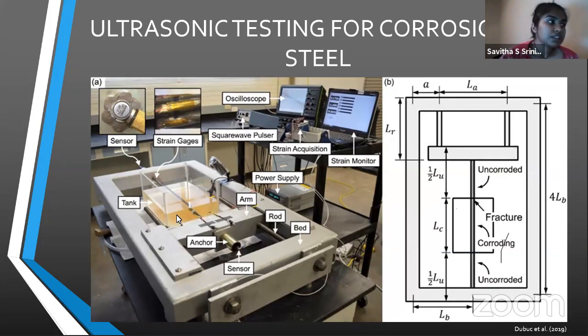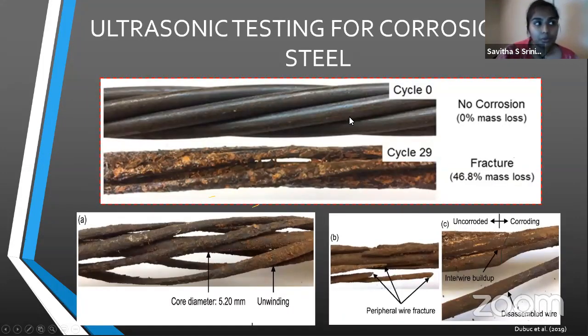This is another way of using the ultrasonic pulse velocity method. What we have here is a water tank with salt water in it and a steel strand going through. Our goal was to force this strand to undergo accelerated corrosion and then run an ultrasonic pulse through it and measure the change in stress due to corrosion, and also calculate the stress using stress and strain, and then compare the two methods. Here we see the sample before corrosion and after corrosion. Once the fracture happens, you have the outer strands just disassembling and the central strand is still there.